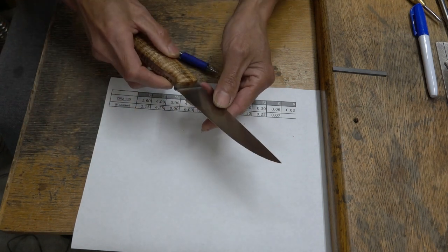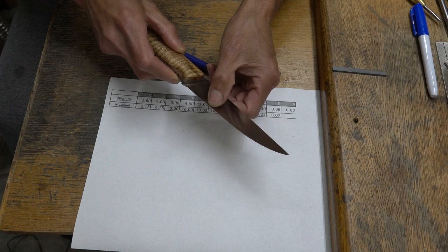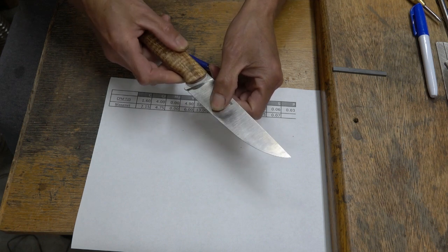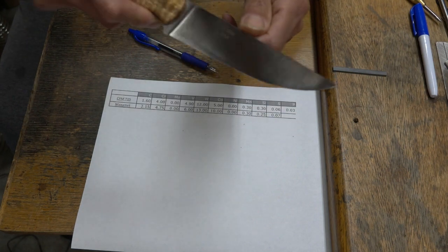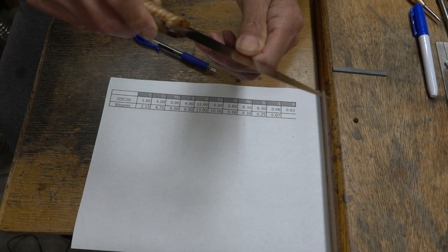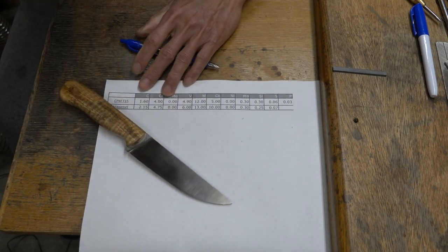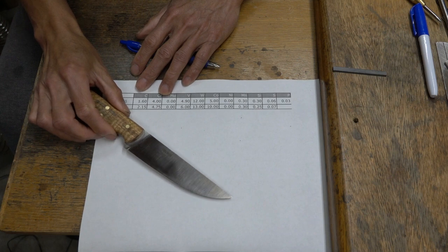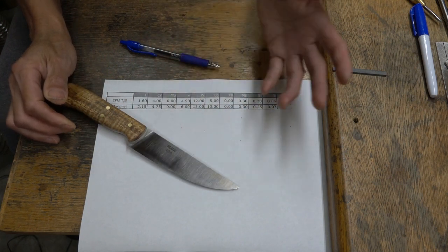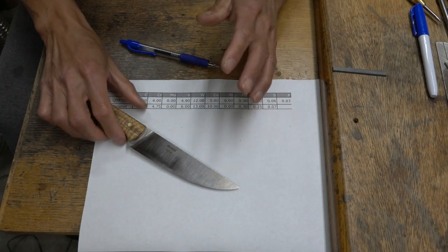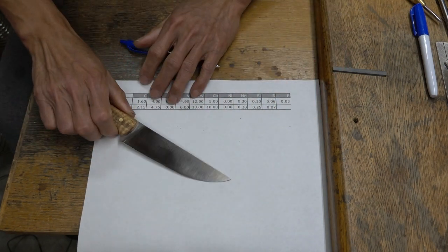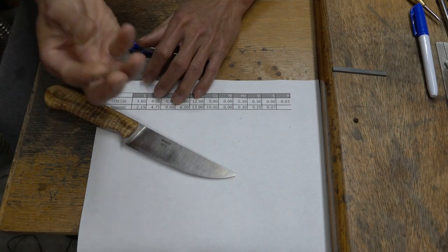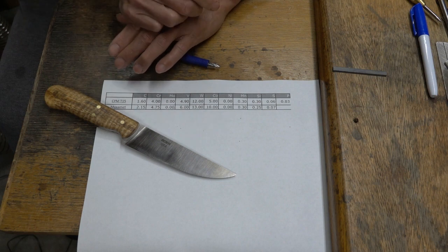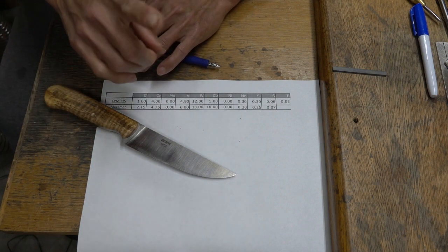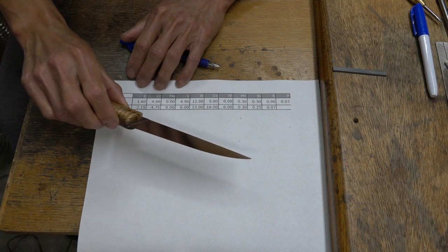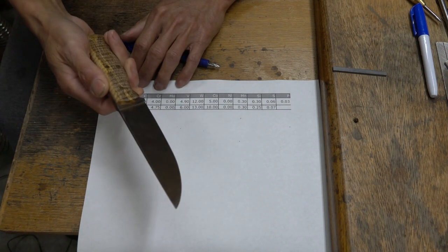Basically, for this edge here, behind the edge right here, I put in 14 degrees per side, and you can hardly see the sharpening bevel because it's thin. It's less than 10,000ths of an inch there. And I pretty much cut up the whole chicken, go through the bone. I don't chop, I press down. And there's no ding, I just cut into the bone, everything like that. I did not cut through the thigh bone, to be clarified. But overall, I want to cut it as long as I can and see how this holds up.